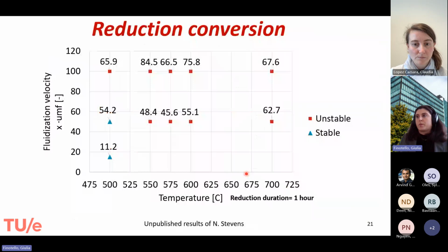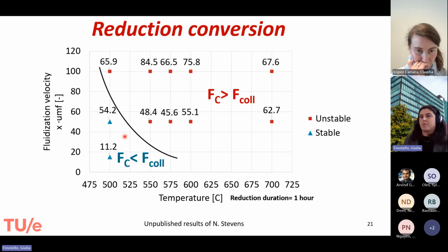So to finish up with the fluidization part, we did also some reduction conversion. You can clearly see we did the reduction experiment for 1 hour at different temperatures, and also at different UMF, so increasing the flow rate, increasing the fluidization velocity. You can clearly see that all these red points are experiments where we experience unstable fluidization, which in some cases ends up in full defluidization, while at only 500 degrees we still have stable fluidization. So we have a map in which here the cohesive forces are larger than the collision forces, and here the cohesion forces are lower than the collision forces.